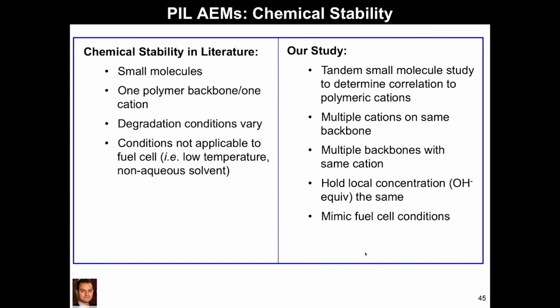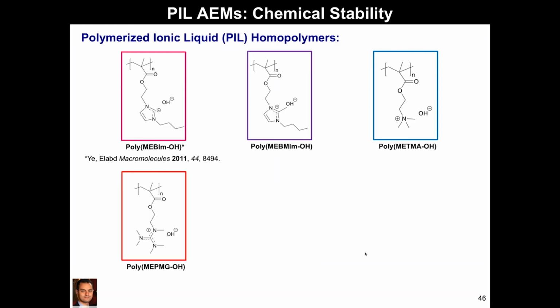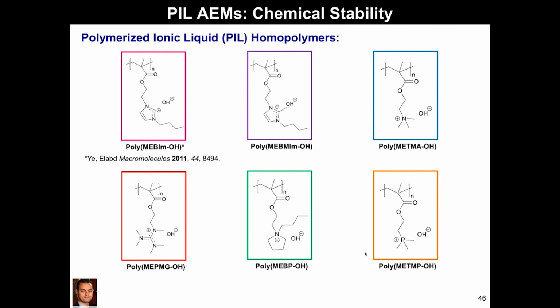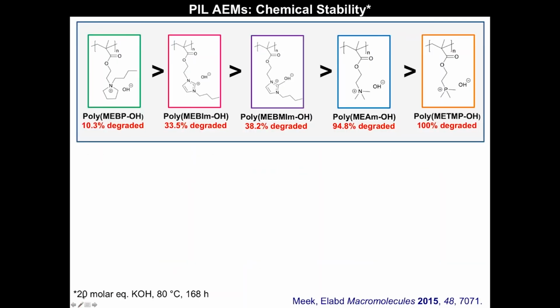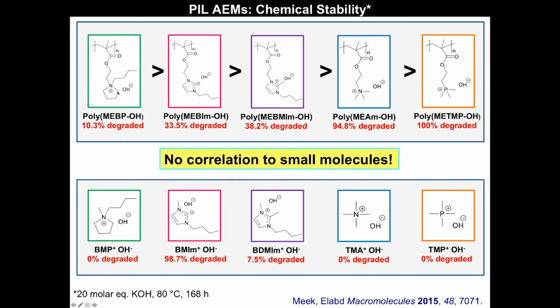So some of the things that we thought of when we did our study, and I've noticed a number of other groups have done similar things as well. So here's just one example of looking at multiple cations on the same backbone, different imidazoliums, ammoniums, guanidinium, piperidinium, phosphonium based. And sort of this is just a summary. So we looked at this at 20 molar equivalents, potassium hydroxide, 80 degrees Celsius for a week. And you can see the imidazoliums, as we'd expect, are better than ammoniums and phosphoniums. But here we saw piperidinium base was actually much better. And we also found that there really was not a clear correlation between small molecules and polymers. So the environment of the polymer and the linkage of the cation to the polymer plays a significant role in the chemical stability, something I think should be noted.